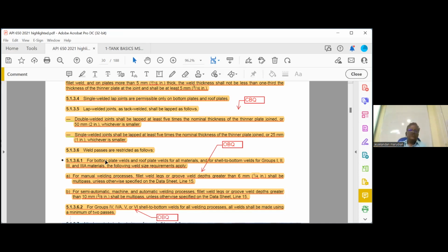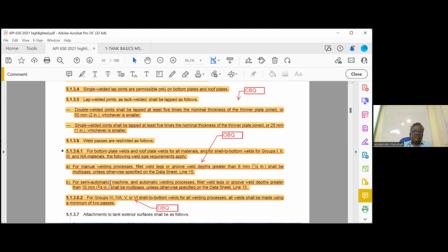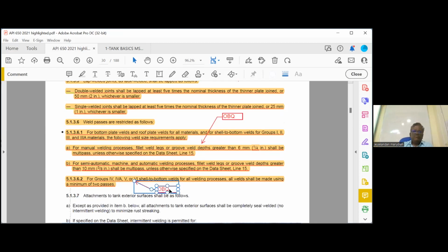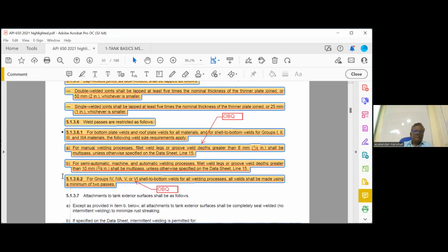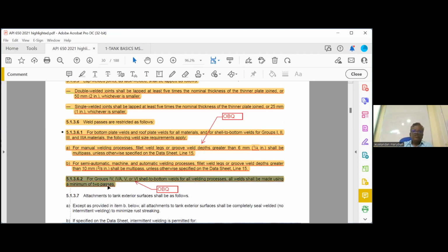Okay, highlight this one. For bottom plates, roof plates and shell-to-bottom in group 1 to 3, the following size requirements apply. These are open book. For manual welding, fillet legs and groove welds greater than 6 mm shall be multi-pass. For semi-automatic, machine or automatic, greater than 10 mm shall be multi-pass. And this is a regularly asked open book question, very important. Highlight this one specially. For group 4 to 6, shell-to-bottom welds and for all welding processes, all welds shall be made using minimum 2 passes. We have to make minimum 2 passes.